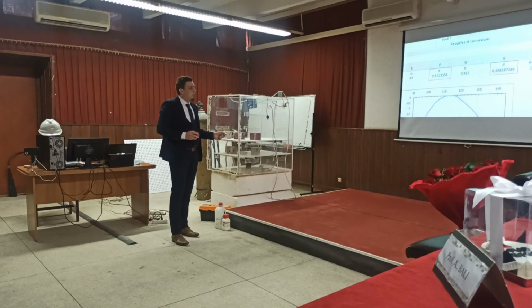We will maximize this equation, as you see here. We use this spreadsheet, the tool, the Solver, and after that we get our parameters, which are the A and the D, as you see here, with the B fixed at 0.415. After that, we replace these parameters into equation 7, and we obtain our conditional probability density function.